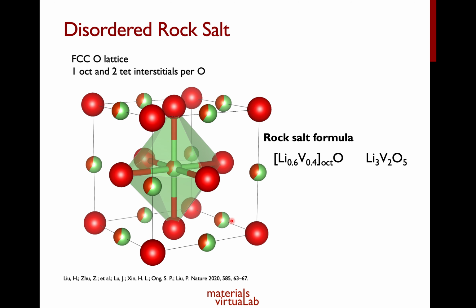So basically, when you occupy all your octahedral sites, you have the rock salt crystal structure, right? So this is actually what is happening in Li3V2O5. In Li3V2O5, you notice that you have a cation to anion ratio of 1:1, which is your rock salt, right? Now, I actually prefer this notation, so I'm going to stick to this notation throughout the rest of my talk. So we can rewrite this as lithium 0.6, vanadium 0.4 in the octahedral site with one oxygen, right? And this gives me my disordered rock salt crystal structure.